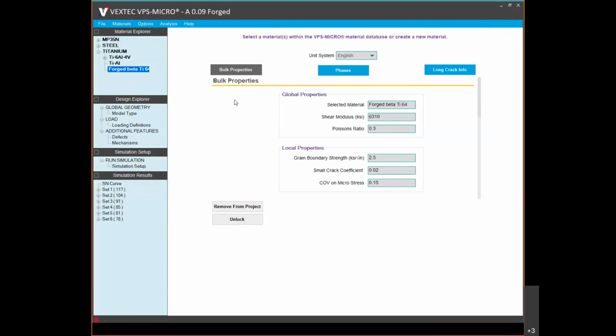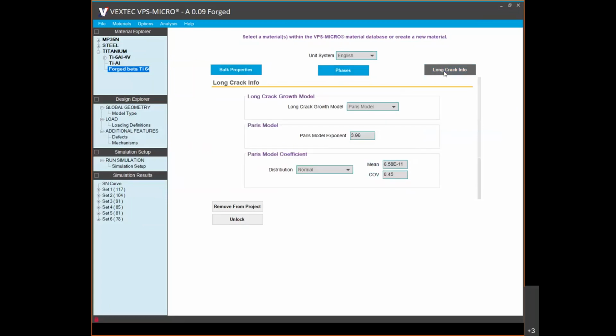On the right-hand side of the interface, you can see all of the modeling parameters for this material. They're organized into 3 main categories: bulk properties, phases, and long crack info. VPS-MICRO's models are truly mechanistic models, as we've said before, and they treat fatigue as a process instead of an event. The bulk properties and the phases tabs in the software develop the models for the nucleation and the small crack stages in fatigue. And the long crack info develops the modeling for the long crack stage.